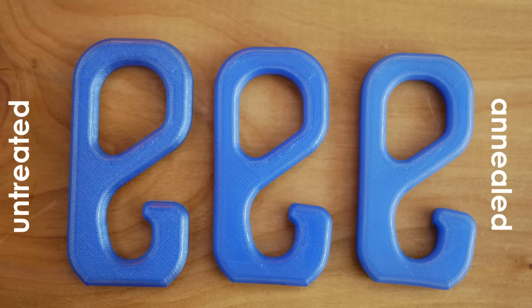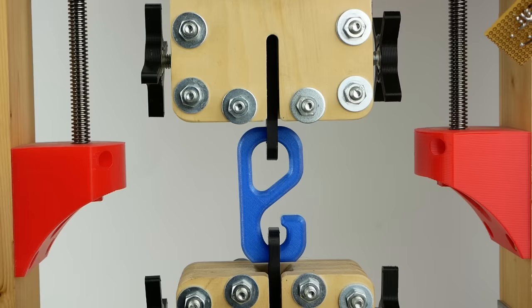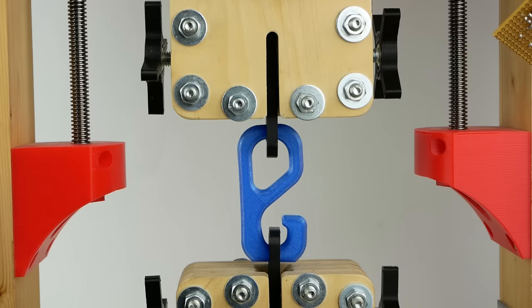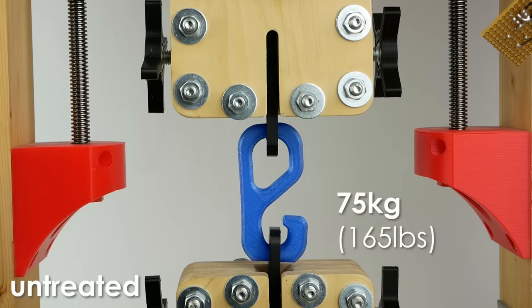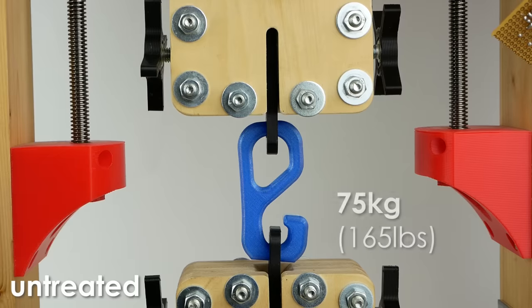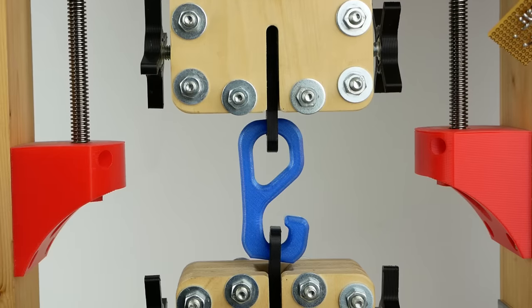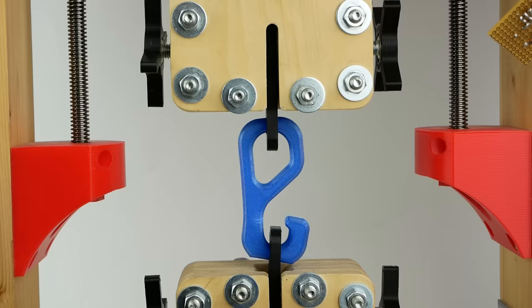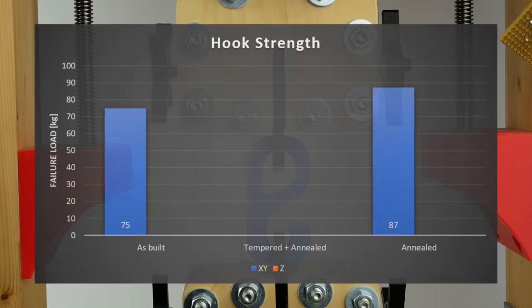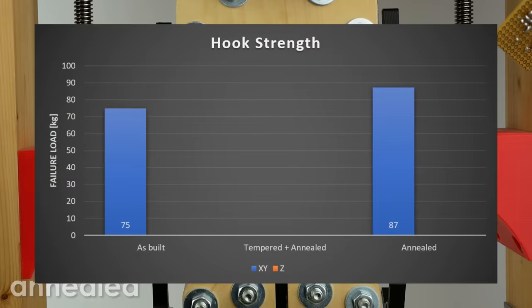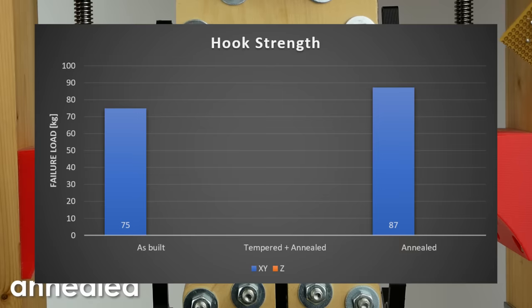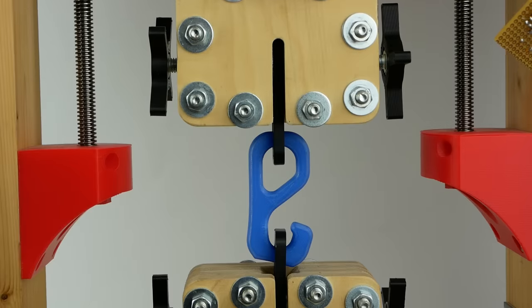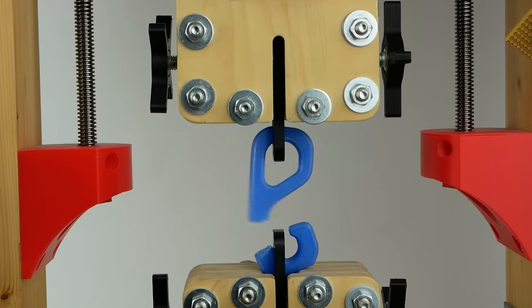Now let's take a look at the results of the test hooks that I used to test a more realistic load scenario with tension and bending. So at first, the lying hooks. The untreated one failed at 75kg of load whereas the annealed one was able to bear a good 16.2% more and ripped at 87kg of force. This improvement is significant and very interesting but I have to say that due to the shrinkage of the hook the bending moment slightly decreased which spoils the results a little. But still a good improvement.